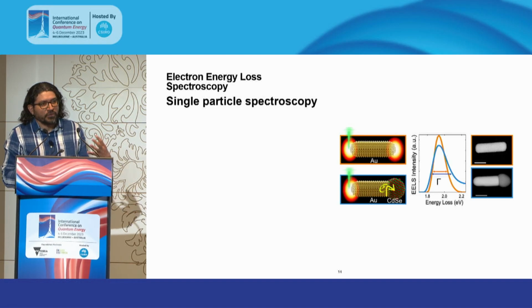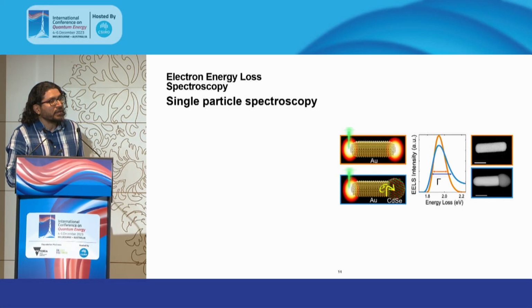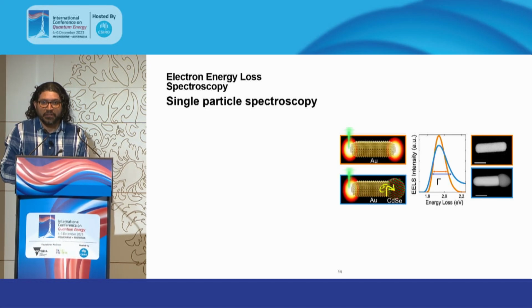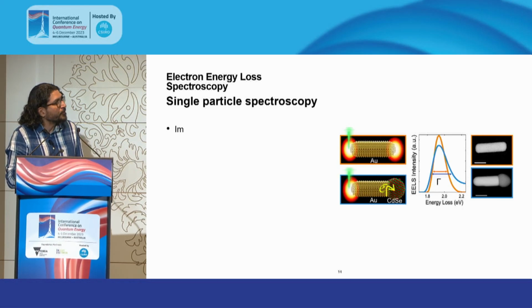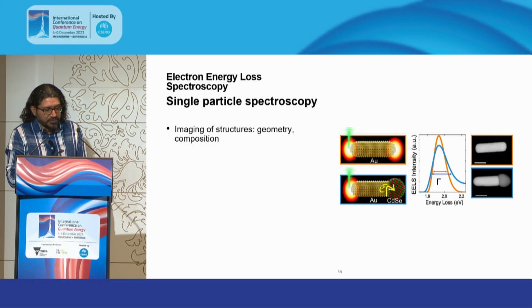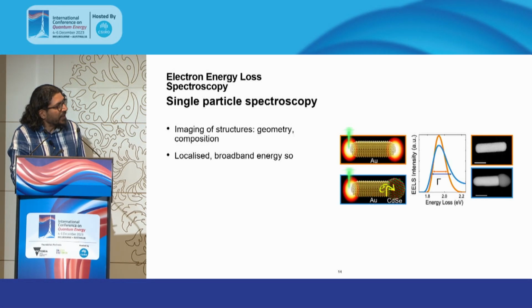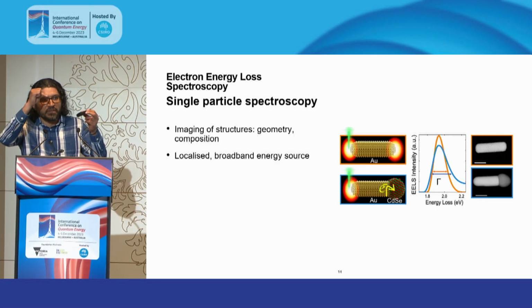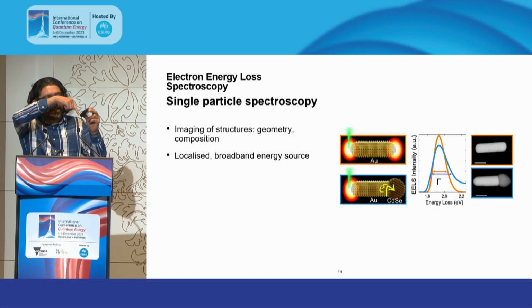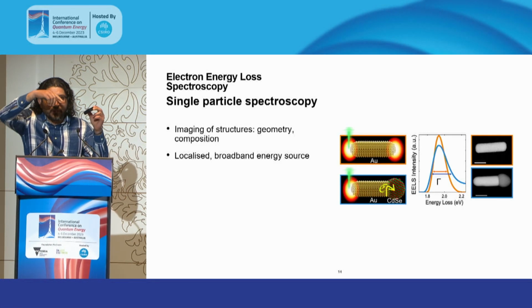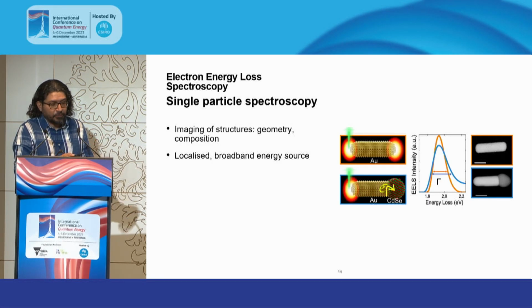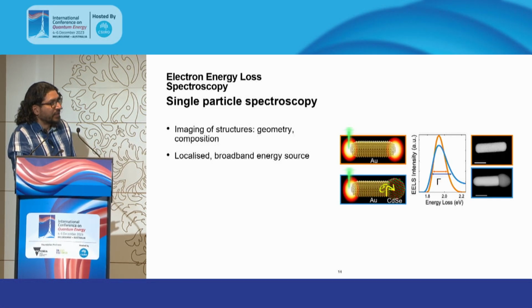To characterize the process of conversion of plasmons into charge-separated states, we use electron microscopy in the form of electron energy loss spectroscopy. So with this technique, we image the structures. We get access to the geometry and composition of such structures in the electron microscope. We then use the electron beam as a localized broadband energy source. And the advantage here is that the electron beam is way smaller than the actual particle. So we can park the beam around the particle and actually map out where the energy goes as we excite the particle with the kinetic energy and electric fields of the electron beam.